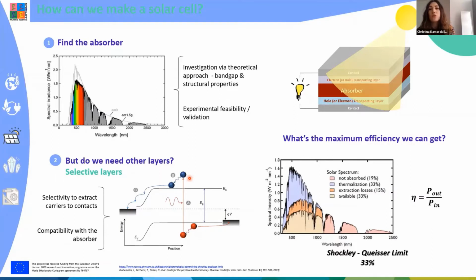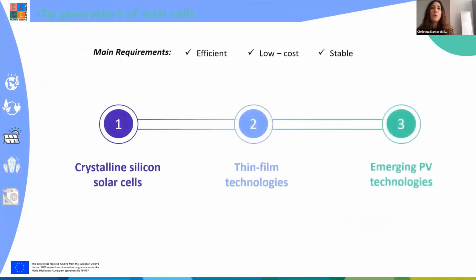Then we have some losses due to photons that have not been absorbed because they have energy lower than the energy bandgap. And some losses around 15%, which are extraction losses and come from resistances to the selective layers or the contacts. So the available percentage is 33% and it's called the Shockley-Queisser limit. So, of course, a solar cell, in order to be commercialized, needs to be efficient, low cost, and stable.